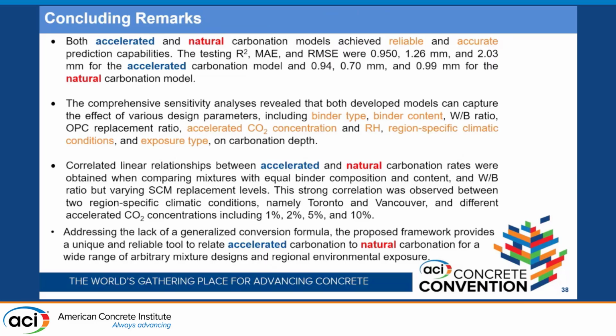So in summary, both accelerated and natural carbonation models were able to accurately and reliably predict the accelerated and natural carbonation depths, and they could capture the synergistic effects of different mix design parameters and environmental condition parameters on the carbonation process. With the results, we could actually establish a linear correlation between the accelerated and natural carbonation for different binary blended mixtures with fly ash and slag.